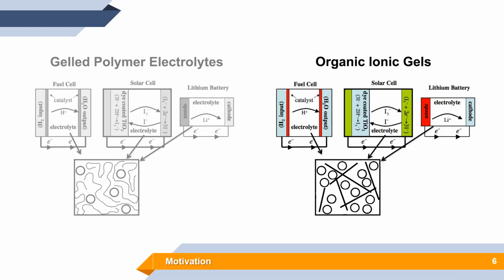The main difference between polymer systems is that these molecules use physical interactions to create a gel state. This can be hydrogen bonding, van der Waals interactions, pi-pi stacking, and so on. And the physical nature of these interactions gives the advantage over polymer ones because these interactions are reversible. By changing the temperature of the system, we can go from liquid to the gel state and vice versa. And this gives us the possibility not only to recycle those systems, but also preserve their lifetime.